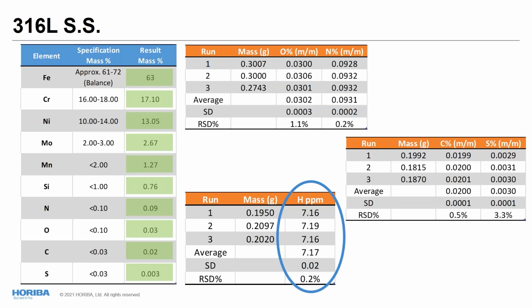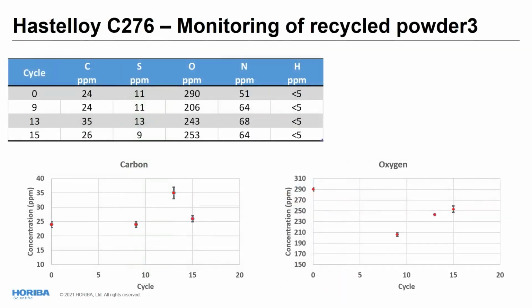precision on the measurement, with even at 7 ppm hydrogen, we were able to achieve a sub ppm precision on the measurement. That's really nice because when you're able to measure at such a precision on low values of hydrogen, you are sure that you will be able to monitor your process and identify any contamination very early if it happens. And the last example I wanted to show and to share with you was the monitoring of the recycled